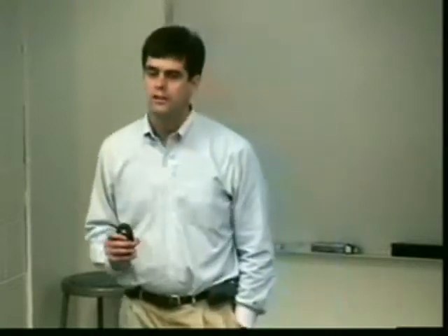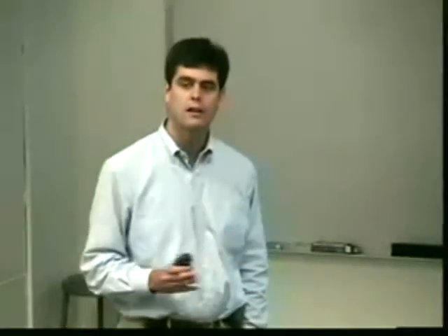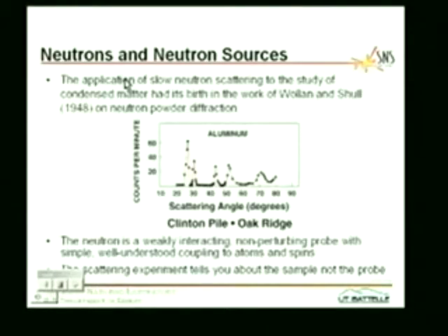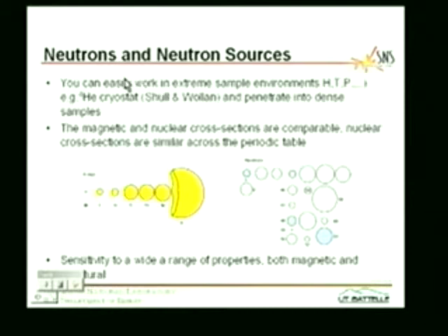It's very simple and well understood. From the point of view of a biologist or a condensed matter physicist, a nucleus is a point object, and so the scattering potential that you scatter from is a delta function. So it's the simplest possible thing to analyze mathematically. Similarly with the spins, it's just dipole-dipole interaction. You can write down exactly what the interaction is, and that means that the scattering experiment tells you about the sample and not the probe, or not the probe plus the sample. It's a very clean and interpretable sort of thing.